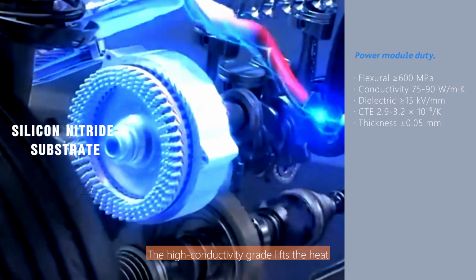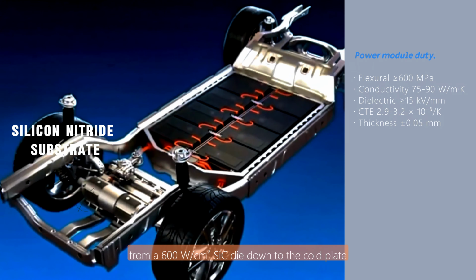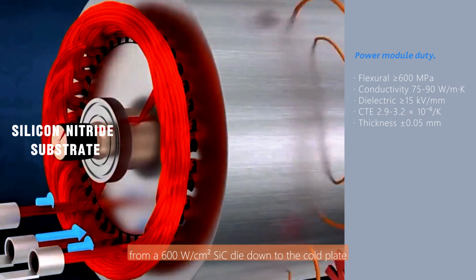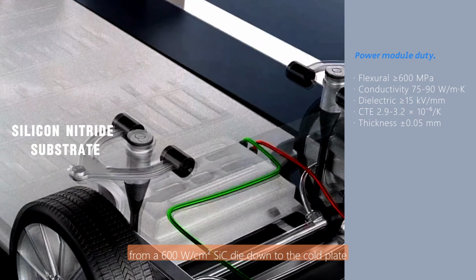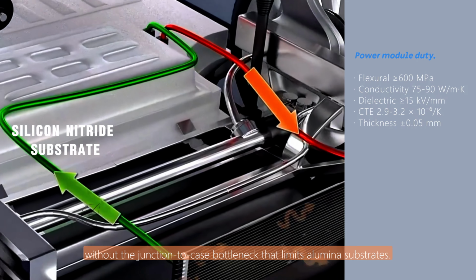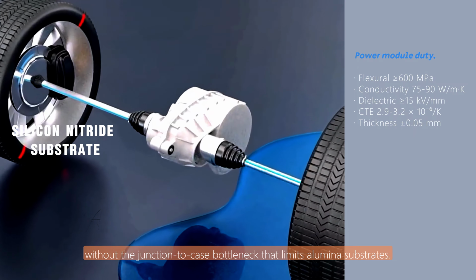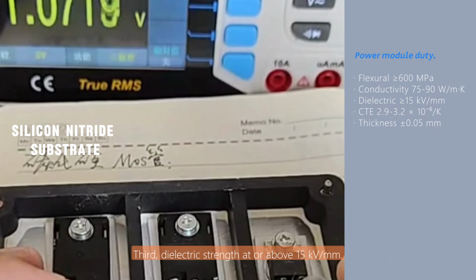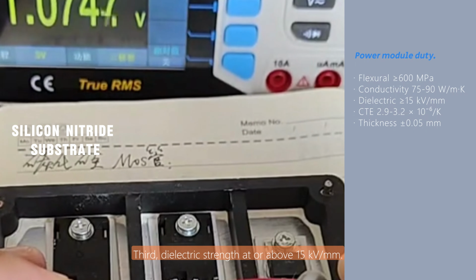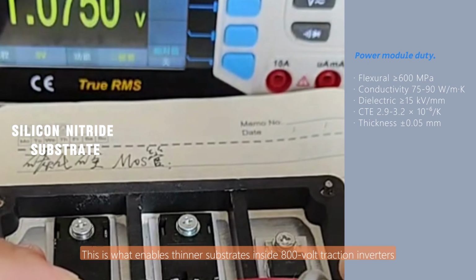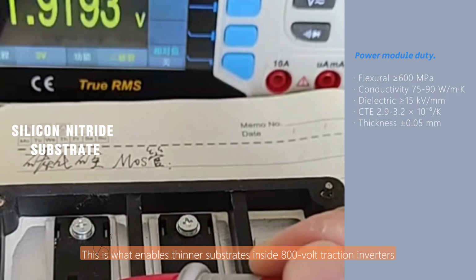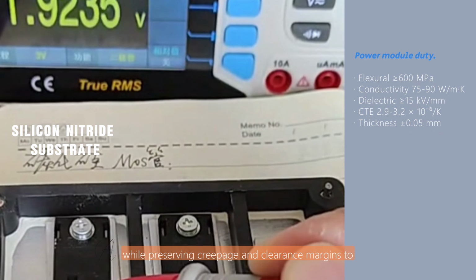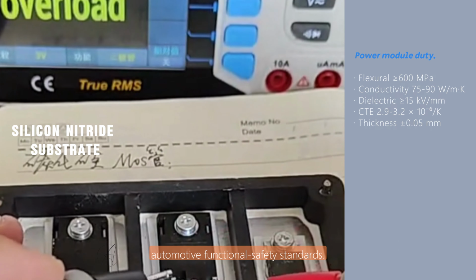The high conductivity grade lifts the heat from a 600 watt per square centimeter silicon carbide die down to the cold plate without the junction to case bottleneck that limits alumina substrates. Third, dielectric strength at or above 15 kilovolts per millimeter. This is what enables thinner substrates inside 800-volt traction inverters while preserving creepage and clearance margins to automotive functional safety standards.